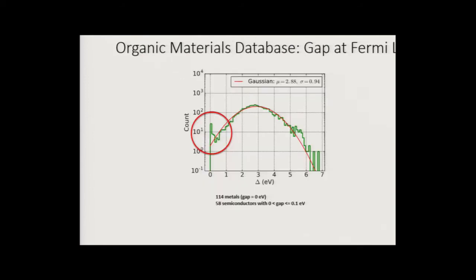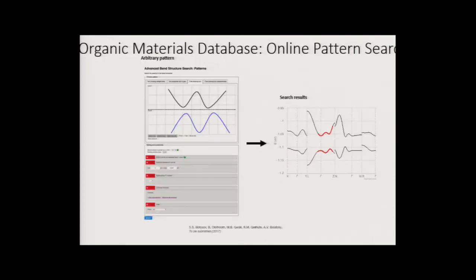One thing the database forces you to ask, once you have this kind of massive amount of data: a typical organic material is an insulator, a wide band insulator. The question is, what is the typical gap? What you find is that the statistics of the gaps lie out in a very nice, beautiful Gaussian, centered at about 2-3 electron volts with a width of 1 electron volt. And we do have outliers, which show that maybe we have a lucky chance. There is a slightly elevated presence of metals with small gaps. And we can have an online pattern search.